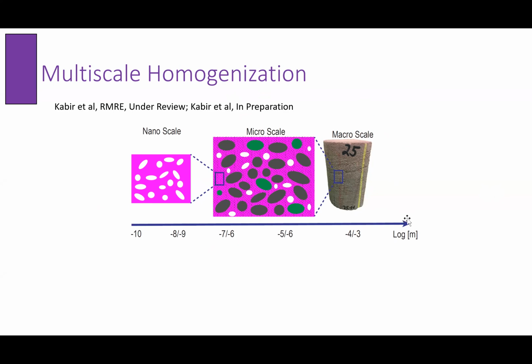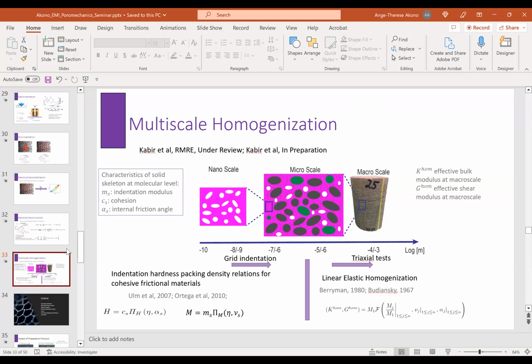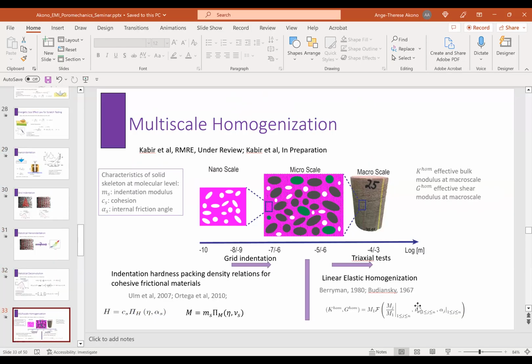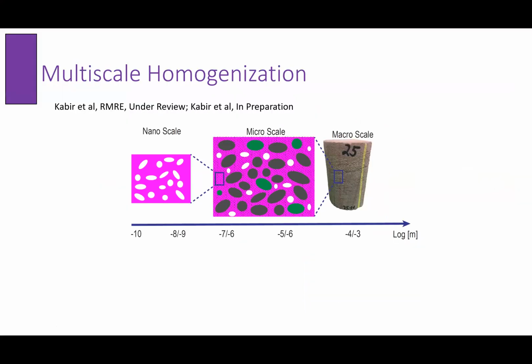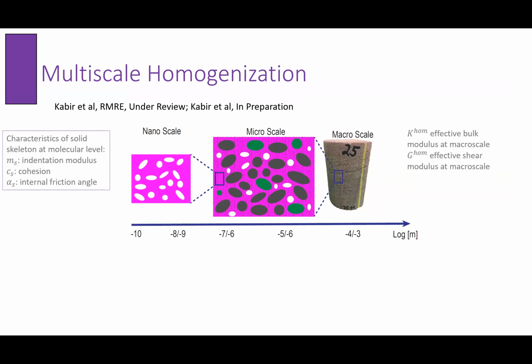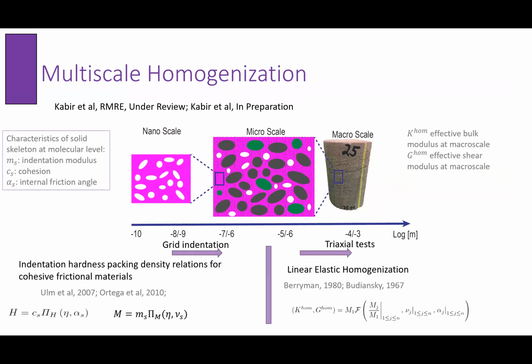In this case, we're going to go from the nanometer length scale all the way to the micrometer length scale. And then we're going to couple this with homogenization. So if we want to go from nano to micro, we're going to resolve it using grid indentation, but also micromechanical modeling. And then if you want to go from micro to macro, to have an agreement or handshake with triaxial testing, we're going to use linear elastic homogenization. Okay.